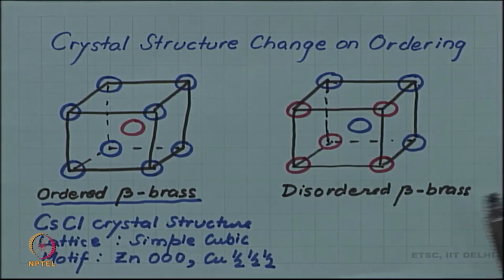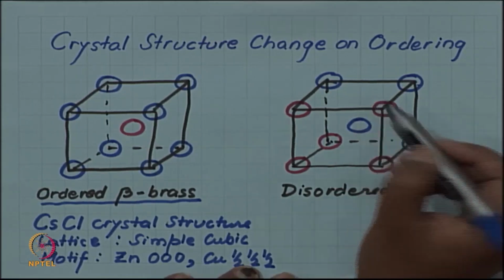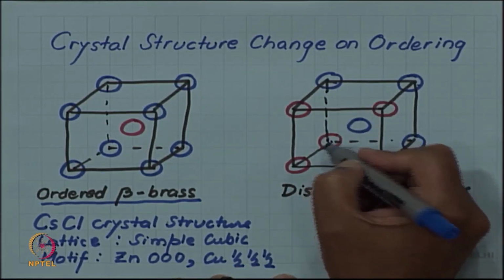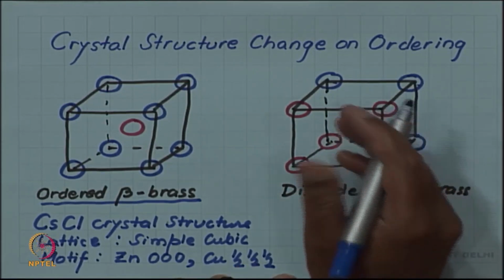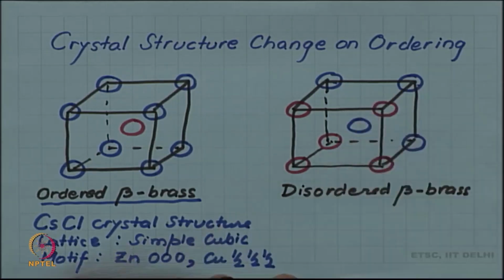However, from all practical points of view, this still behaves like a crystal, and if we look at an X-ray diffraction pattern from this crystal, it will look like a body centered cubic structure. Why that happens is that, because of the randomness, the corner atom and the center atom become statistically equivalent, because there is a 50% probability.